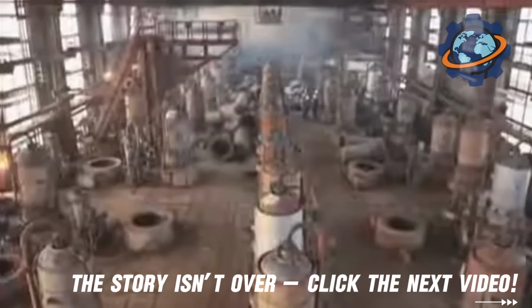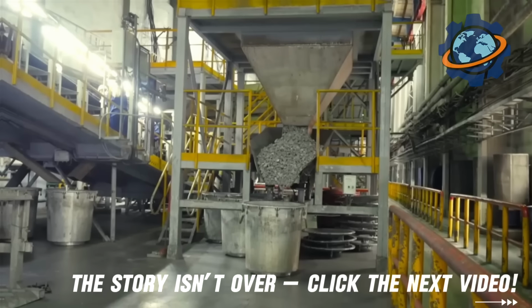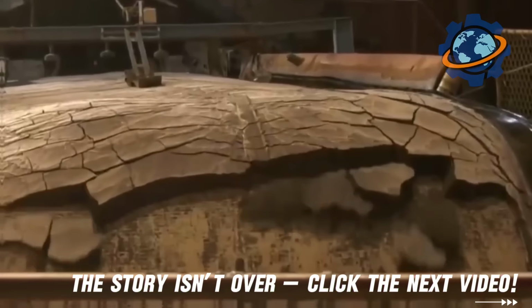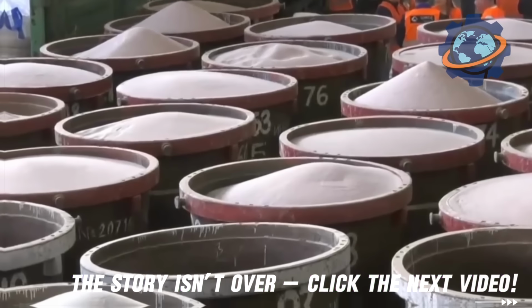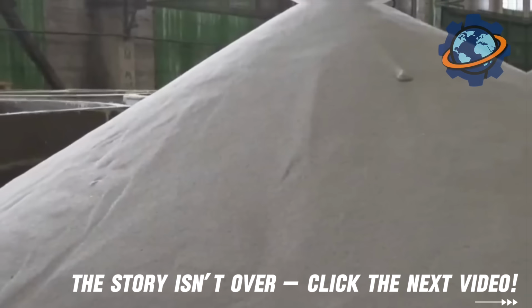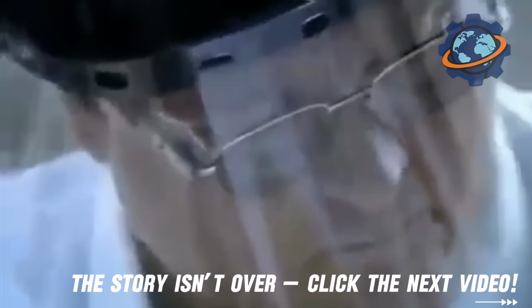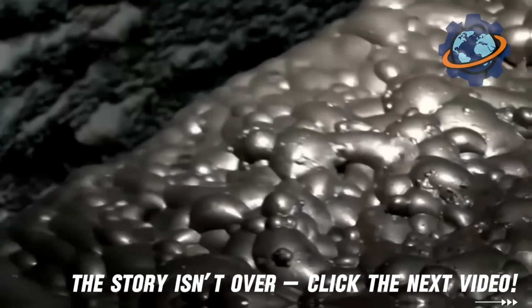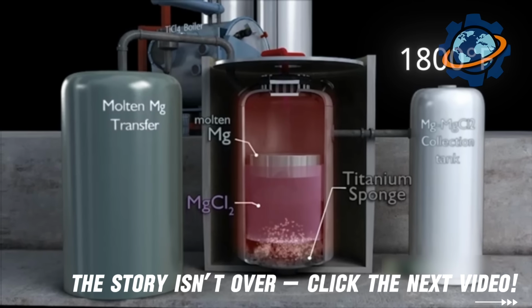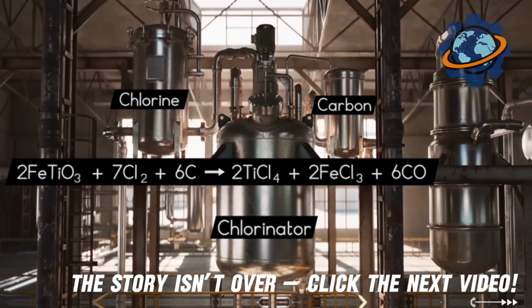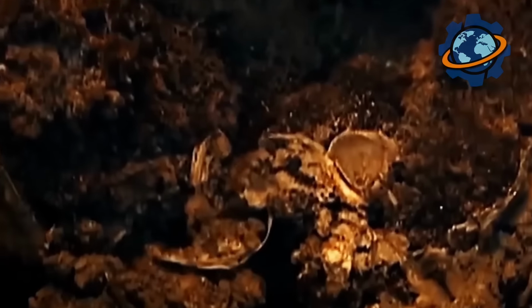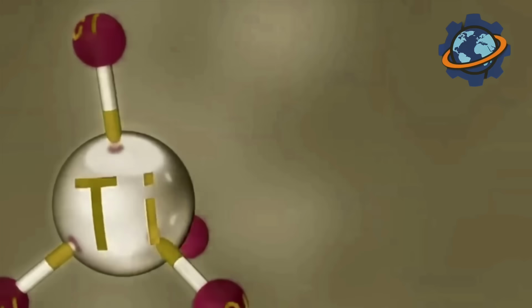The initial stages of titanium production are based on a complex, multi-step technological process that begins with the extraction and preparation of titanium-bearing raw materials, mainly ilmenite and rutile. These minerals contain titanium oxides, which must be converted into chemically pure titanium tetrachloride. To do this, the titanium ore concentrates are chlorinated in fluidized bed reactors at a temperature of 1,800 degrees Fahrenheit, where carbon and chlorine gas react with the raw material to form titanium tetrachloride and carbon monoxide. This tetrachloride contains impurities of other metals, which are removed by distillation to obtain high-purity technical titanium.